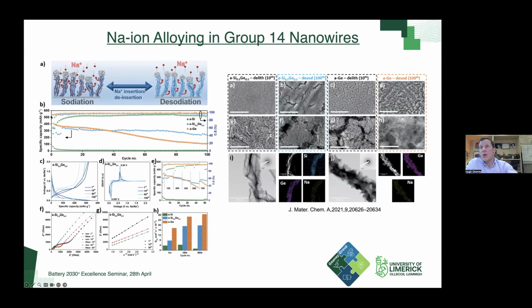So I guess the take-home message here from the electrochemistry is that amorphous germanium in a pure sodium ion half cell gives around 400 milliamp hours per gram, depending on the exact anode configuration that you have. But what you see over time is that this capacity drops off. I'll show in a second with the SEM that this is linked to material-related processes, whereas the alloy in between, silicon germanium, is more stable in terms of its capacity retention.